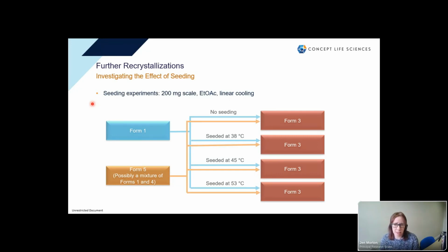We used ethyl acetate. We used a linear cooling ramp as in the Crystal16, and we took forms 1 and 5 and put them into a variety of experiments where we seeded at different temperatures. And in fact, an experiment where we didn't seed at all. And you can see that all of these experiments generated form 3 every time.